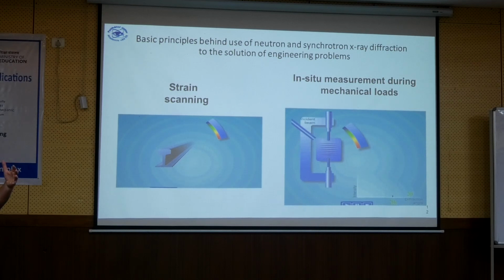Like X-ray diffraction, you see the diffraction patterns which are reflections of planes in the material. And if you have two phases, austenite and martensite, you have different kinds of diffraction patterns. So if I pull the crystal, I can track this diffraction. And I use the basic principle which is shown in this right experiment. Hopefully it will start. So if you irradiate the sample by neutrons, you follow the diffraction over here, and you can see the position of the peak. So this is now in compression. I will run it again because I didn't have time to. But it will go automatically.